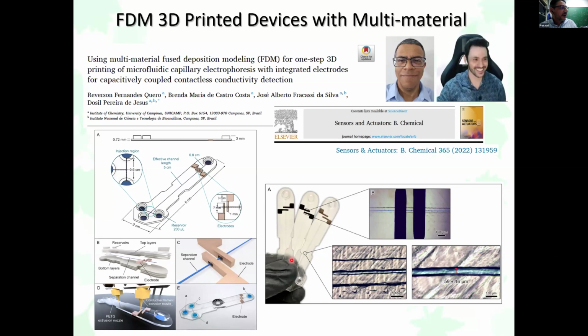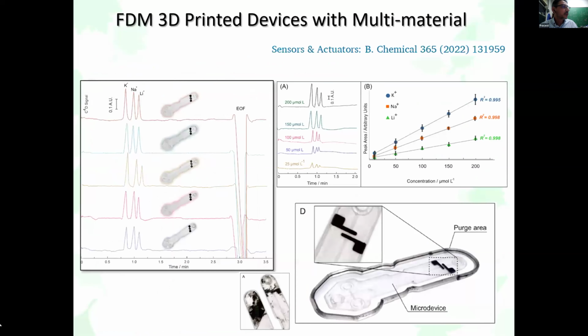So this is the final appearance of the device. You can see here the microchannel. In this work, Reverson got a little smaller microchannel. Here is 59 microns. And here the electrodes. These electrodes are for contactless conductivity detection. So in contactless conductivity detection, we apply one signal to one electrode and get the transmission through the channel.